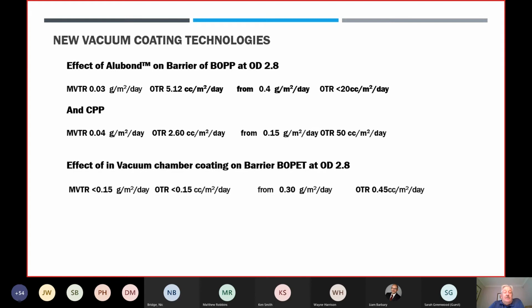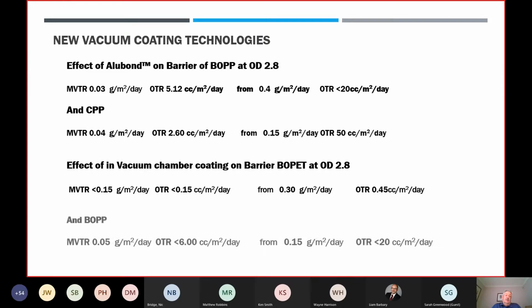And the effect of in-vacuum chamber coating on barrier BOPET, with an optical density of 2.8. Again, a halving of the moisture barrier and reducing the oxygen transmission by over 66%. And for BOPP, again, you're getting similar figures to what you would with the effect of Alubond. As I said, there's only 2 suppliers of this in the world. One of those does market it quite readily, and believe it or not, made a lot of the polyester. It's being used in industrial uses at the moment. The only one caveat with this is because it's using